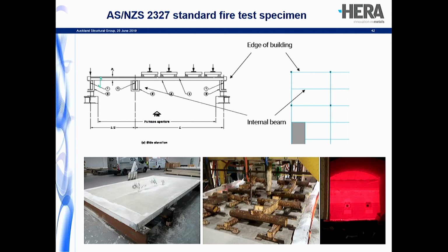And this arrangement's been in use definitely in the UK for the last 30 years. And essentially what it's intended to do is represent the worst case of a slab at the edge of a building. So you would basically have some continuity of the slab at the first internal support. So basically what the test setup on the left-hand side has is that you have the specimen over a furnace. The span of the slab is loaded, and at the far end, the slab is held down in position. So basically, as the slab deflects, it stops the end of the specimen lifting up, so you actually get hogging moments developing over that internal support.